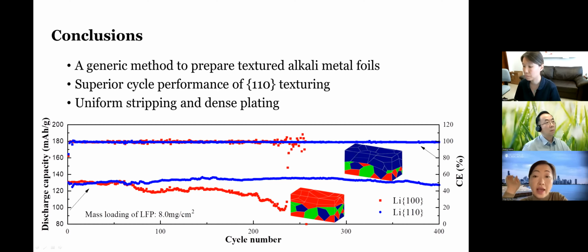Yeah, and I also agree with you. The SEI, organic or inorganic, is not the key. It's how these species are distributed. So it's very fascinating to see you do have a thin inorganic layer, but it's quite stable in 110.